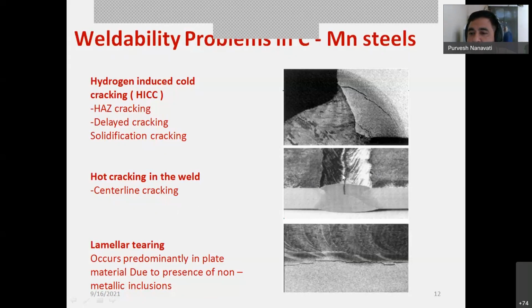You see two plates joined by this weld joint, and you see at the center there is literally a center line crack. This is solidification cracking. And in the third figure, you see a very straight crack, right? This crack is a lamellar tearing. That is most of the time found in rolled steel or in steel containing some amount of non-metallic inclusions. So this is lamellar tearing. I wanted to introduce these pictures for a better explanation of the weldability issues.